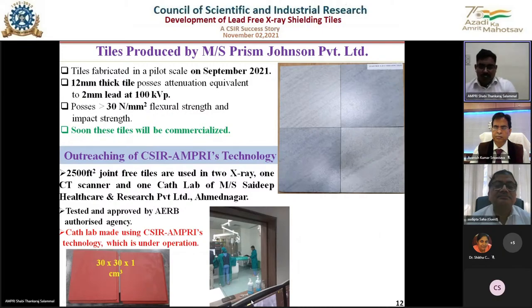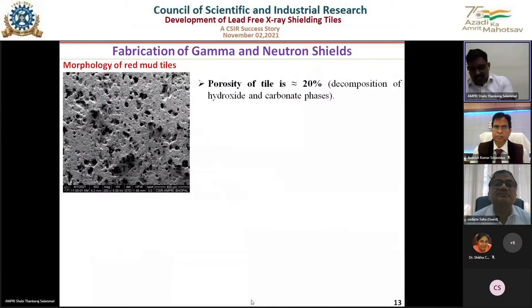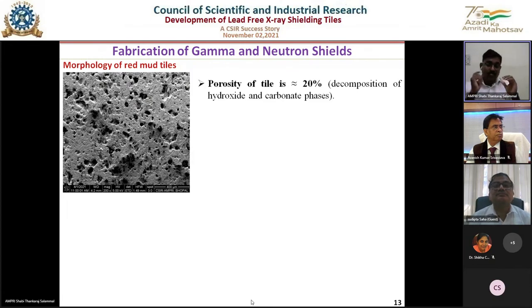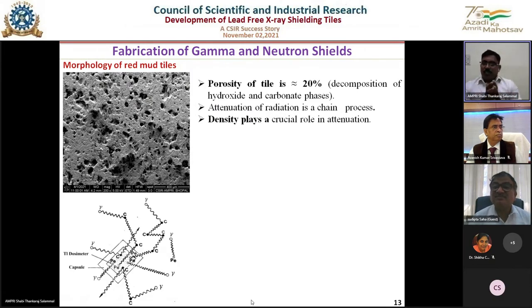As I told earlier, in this red mud tile you can see pores. This porosity is quite high because some hydroxide and carbonate phases decompose and are trapped inside, creating these pores. These pores are not good for radiation shielding applications. For clinical X-ray shielding, up to 140 kVp is fine. But for gamma rays and neutrons, which are very high energetic, we also need high density.